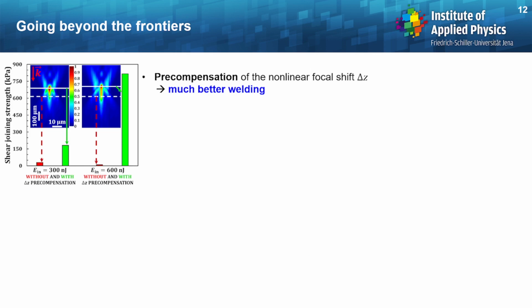Here you can see on this graph the shear joining strength for two input pulse energies, 300 and 600 nanojoule, without in red and with in green precompensation of the nonlinear focal shift delta Z. And the striking feature on that figure is that when you precompensate for the nonlinear focal shift during the welding, then it leads to a much better welding.